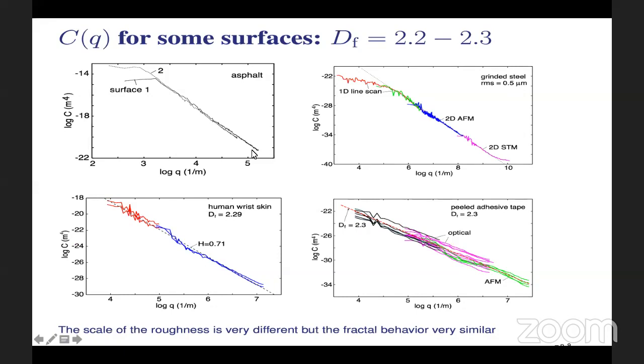Here I show the surface roughness power spectrum of different surfaces. Here it's asphalt, here it's grinded steel, here it's human wrist skin, and here it's a peeled adhesive tape. You can see that there is a power law relationship here, and this slope is in all of the different surfaces. This slope gives you a Hurst exponent, and from the Hurst exponent you can calculate what we call the fractal dimension. You can see the fractal dimension for all the surfaces lies between 2.2 and 2.3. For many naturally occurring surfaces, the fractal dimension is 2.2.